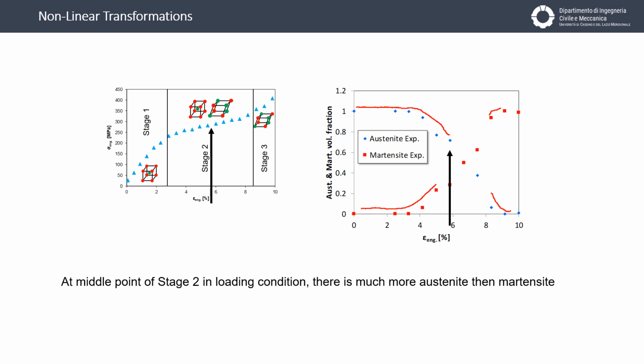For example, at the center of the second stage, sometimes the quantity of austenite and martensite reported in the literature is equal to 50%. It's not true, because as you can see at the center of the second stage, the quantity of austenite is greater than the quantity of the martensite, because the transformation is not linear.